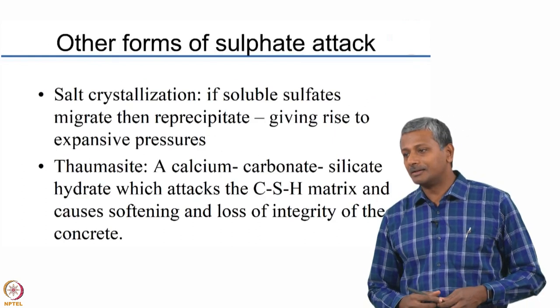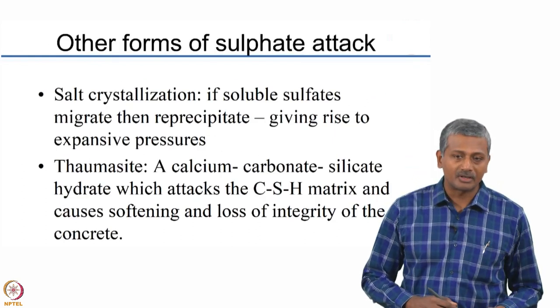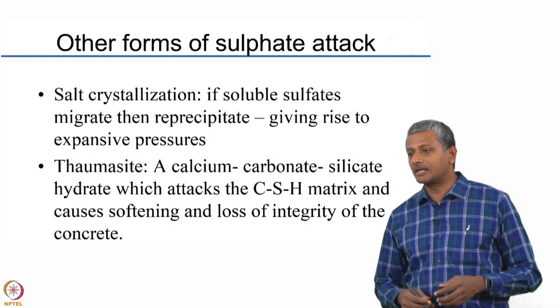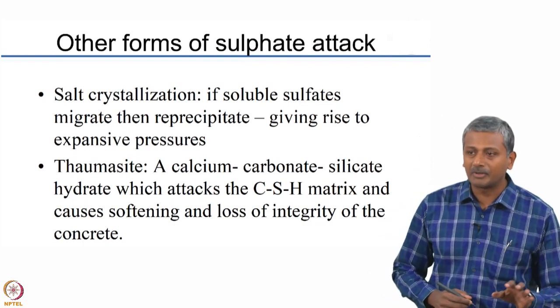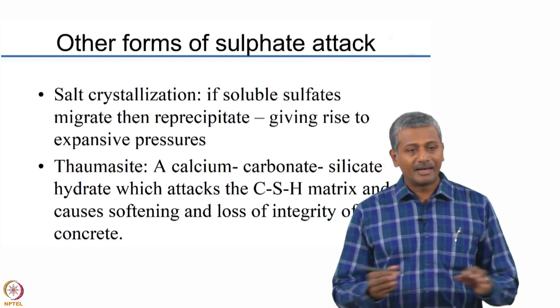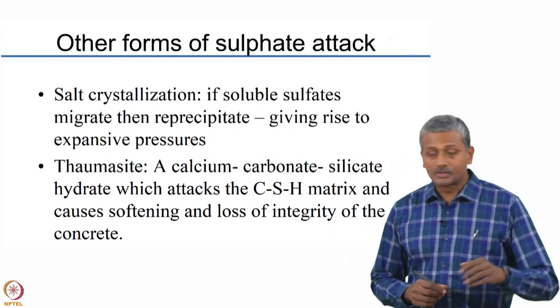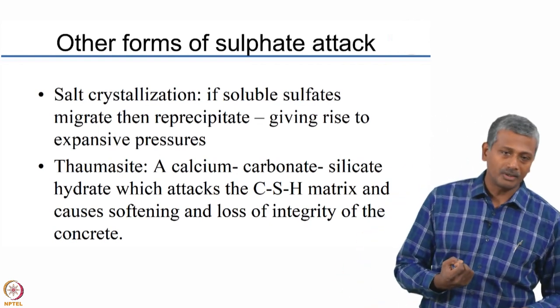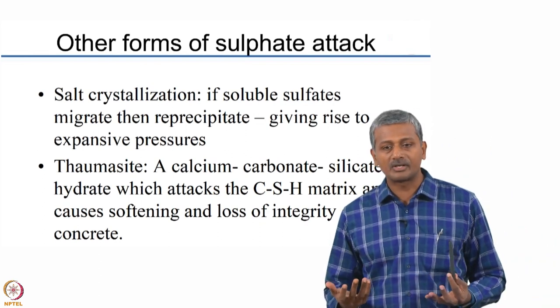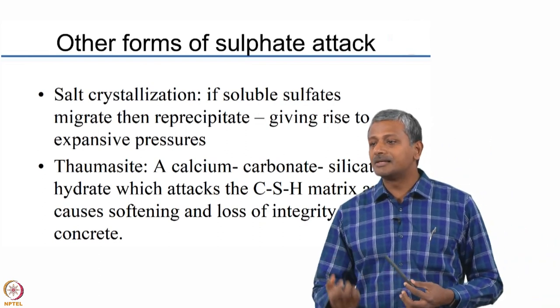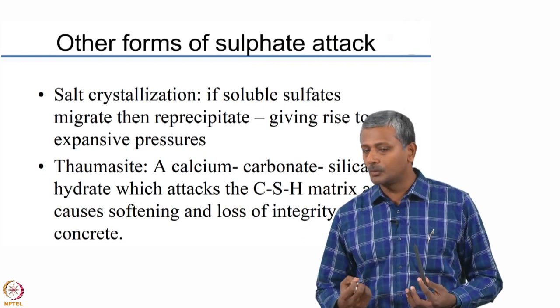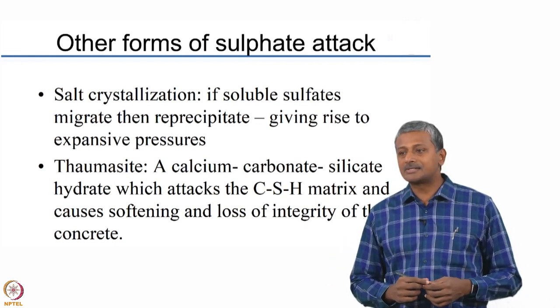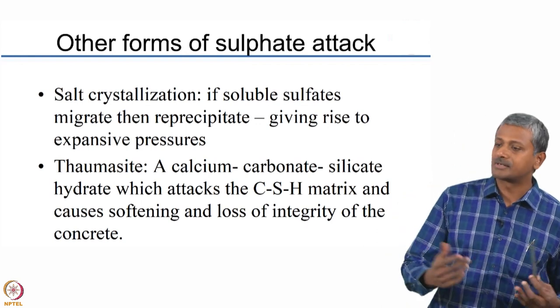Apart from these chemical attacks, you may also get other forms of sulphate attack. There is always an interplay of physical and chemical aspects, but for ease of understanding, sulphate attack has been divided into chemical and physical mechanisms. Salt crystallization is basically a physical mechanism — sulphates enter the pores of the concrete and crystallize when sufficient concentration builds up, causing supersaturation and crystal growth. When the crystal grows within the confined space of a pore, the resultant stress can lead to cracking of the concrete.